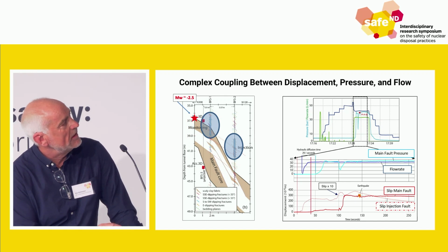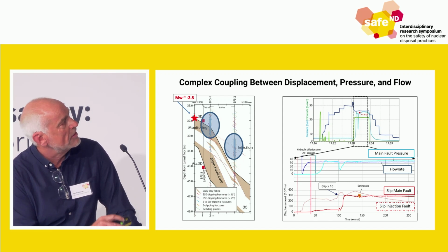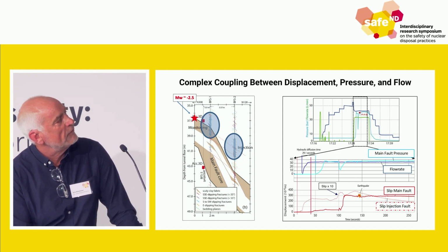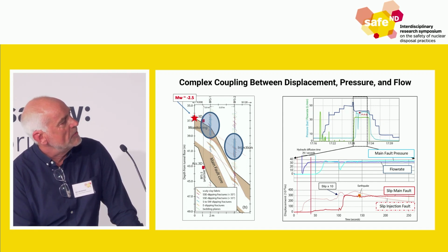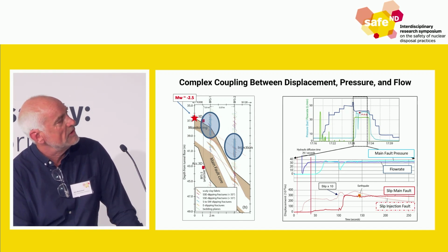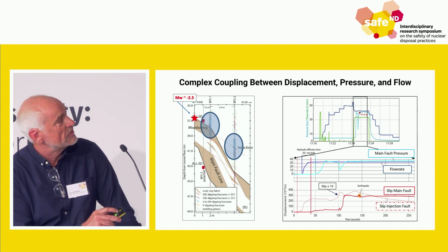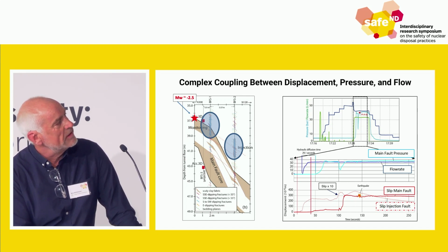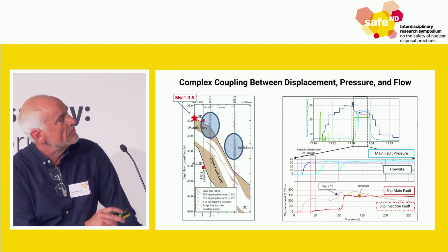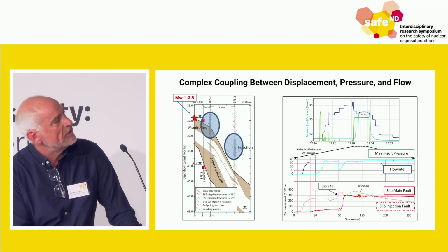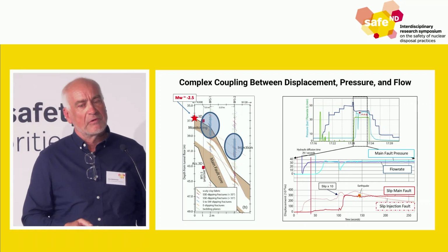This is the flow rate into that injection chamber, this is the pressure here. We can compare that to when we first see displacement. So this is a little bit of displacement here, which then goes up, and this here is later a little bit of displacement. If you pay very close attention, you'll see that this initial early displacement really triggers, a little later, permeability happening. Once that happens, we usually get somewhat later even more displacement and then even more flow.